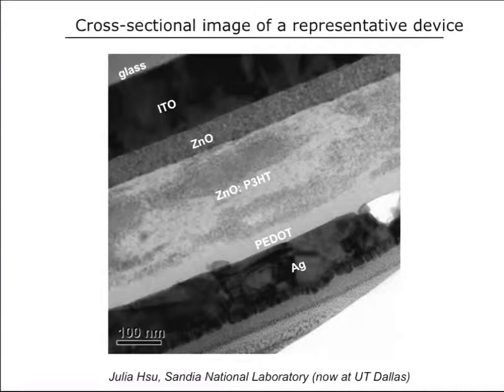So I want to point out that these are really very thin devices. Active layers typically 200 nanometers. That is enabled by the high optical extinction coefficient of organic semiconductors, which is typically over 100,000 inverse centimeters. So we really don't need much material to absorb the light. That's a good thing, because in the balance of charge carrier mobility and carrier lifetime, we only get a carrier distance of a few hundred nanometers out of these devices. So if we tried to make this 1 micron thick, we would suffer from massive recombination. But luckily, Mother Nature is kind to us, and we get the necessary optical absorption.